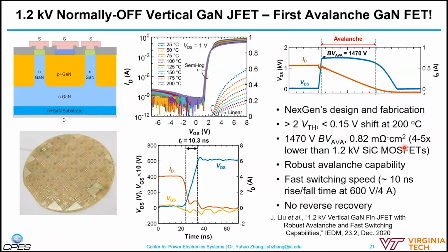Very robust avalanche, and we also did a double pulse test of their devices, with very fast switching speed, about 10 nanoseconds, switching on and off between 600 V and 4 A. Also, the reverse recovery is very minimal.